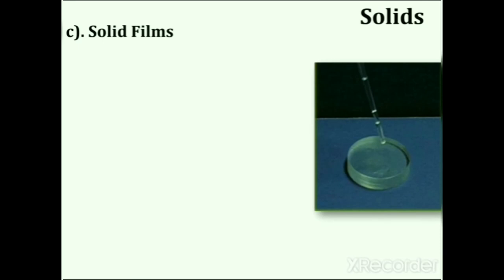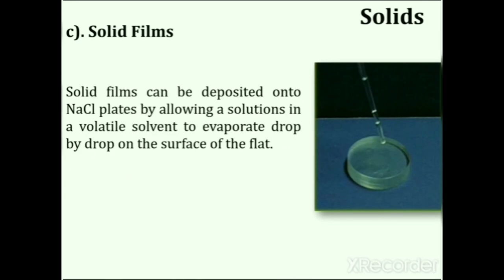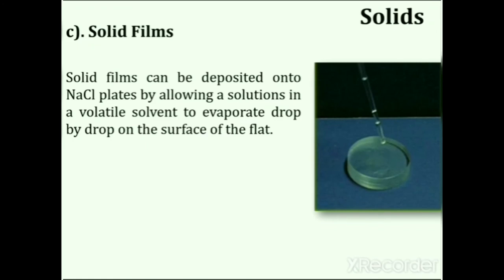Another technique for handling solid samples is making solid films. The sample is dissolved in a volatile solvent and the solution is allowed to evaporate on a heated surface, leaving films of the sample. Solid films can be deposited onto NaCl plates and analyzed by placing them between IR transmitting windows. Polymers and various waxy or fatty materials often give excellent spectra in this way.